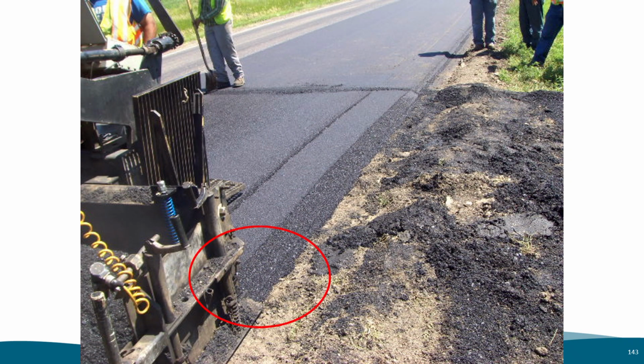Here you can see the change in asphalt that has been laid on the road. This occurred because they weren't up to the correct temperature on their screed heater. If this happens, they should stop for a few minutes to allow the screed to heat up to the appropriate temperature.